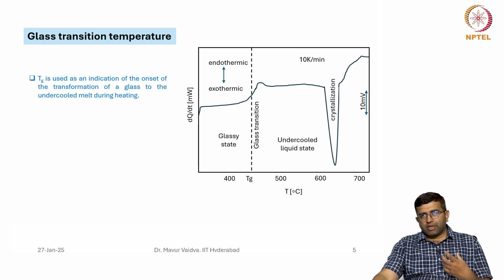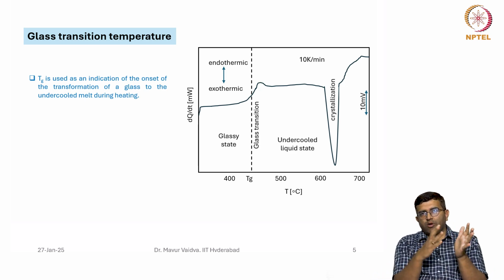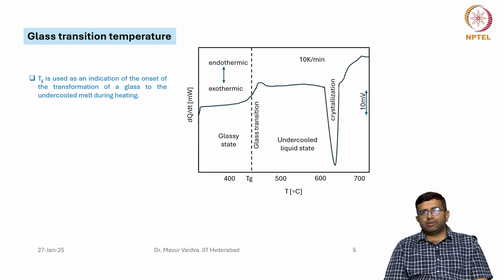Although thermodynamics is not really the subject of this particular course, you can clearly see that there are two transitions happening. One is the glass transition, where the glass goes from the glassy state to an undercooled liquid state, whereas the second is this undercooled liquid becoming a crystal. For crystallization you see a sharp peak, but there is no such peak at the glass transition temperature. Why is that so? How do you differentiate these two?